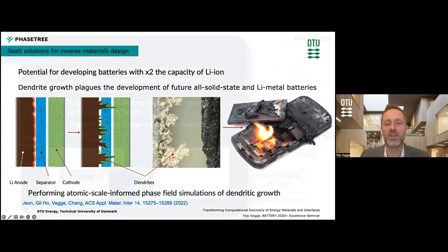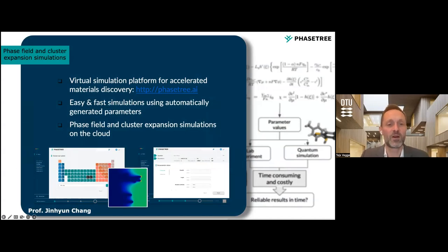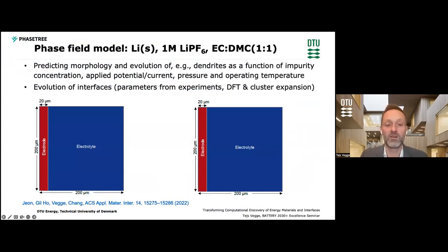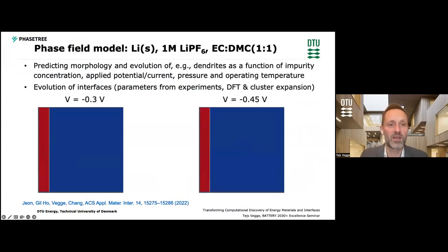Again, making tools that are easy to use, where if you are, say, an experimentalist interested in testing out what a new additive could do to suppress dendritic growth, you really don't have to worry about all the complex chemistry and quantum chemistry behind the scenes. You should have a nice graphical user interface that allows you to check a certain composition of the electrode or the electrolyte, and then run the simulations under the intended operating conditions. So this is the case of a lithium metal anode and LiPF6 salt in an EC/DMC electrolyte, running at different conditions, so different charging potentials.